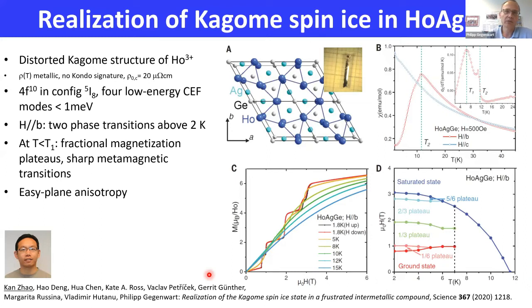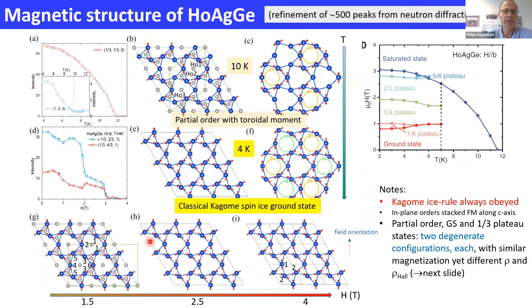Now, thanks to his careful work on the crystal growth over many years with the self-flux method, Kan managed to grow high quality and large single crystals, which we could then use for very detailed magnetic structure investigation by neutron scattering. And here I show you already the outcome of a magnetic structure refinement, which is based on more than 500 peaks detected in neutron diffraction.